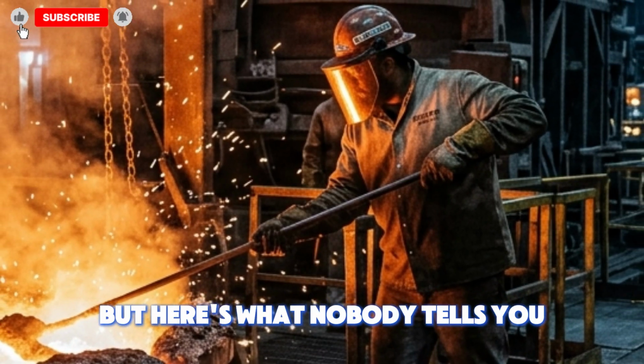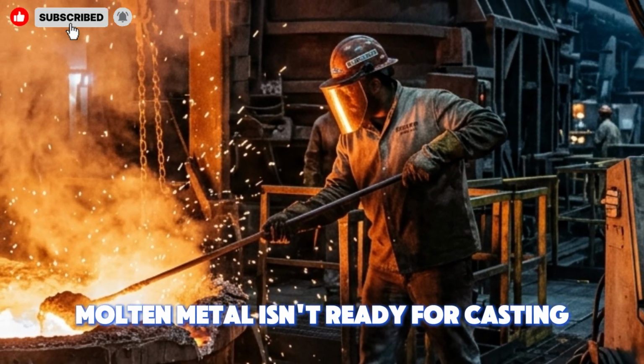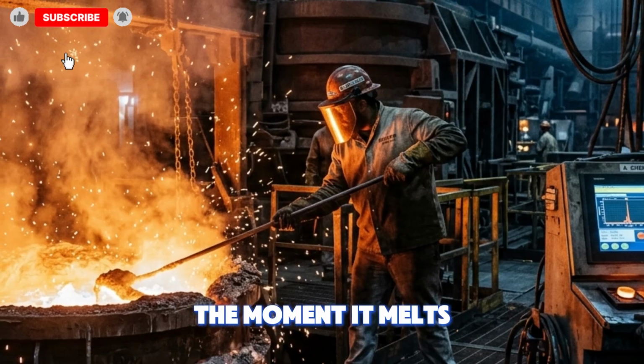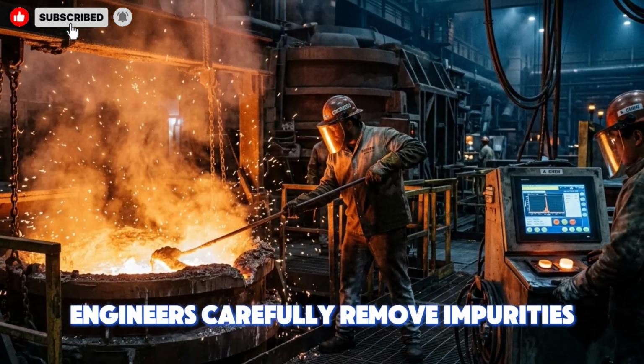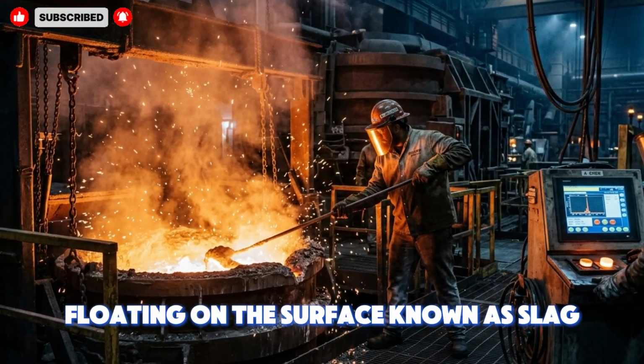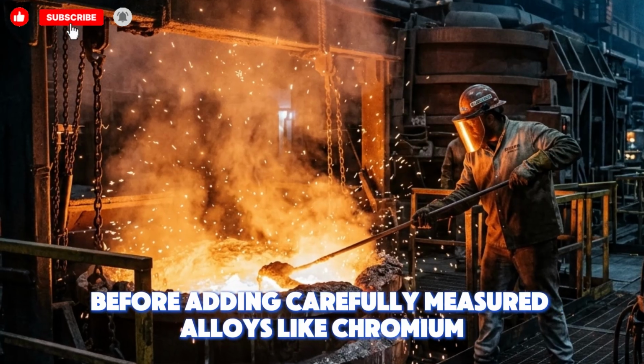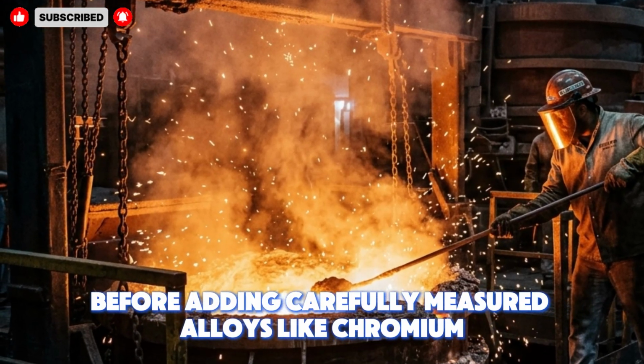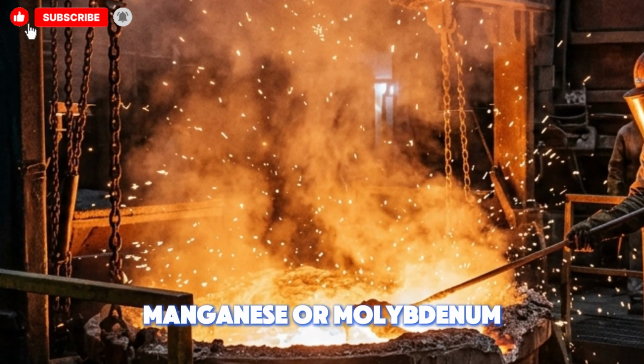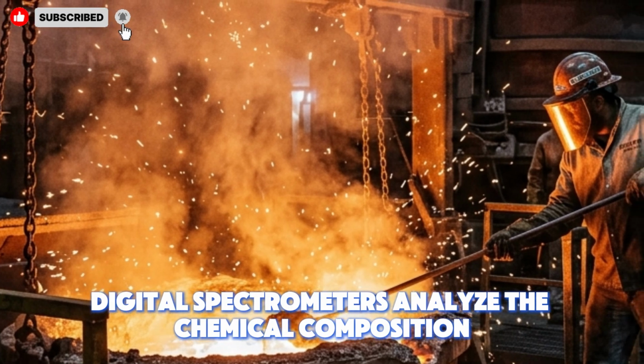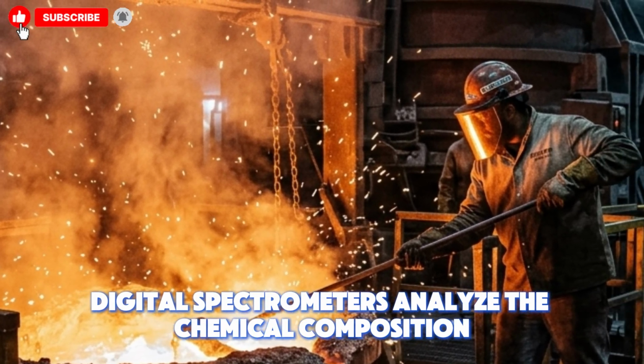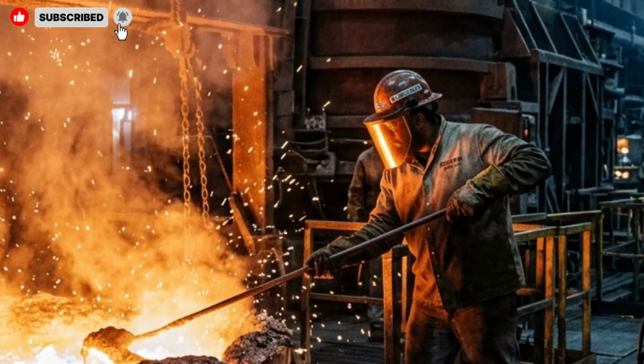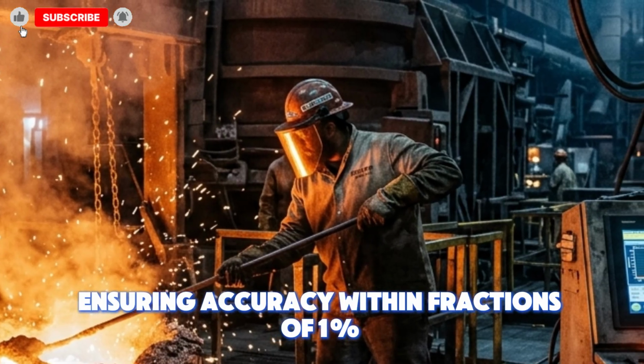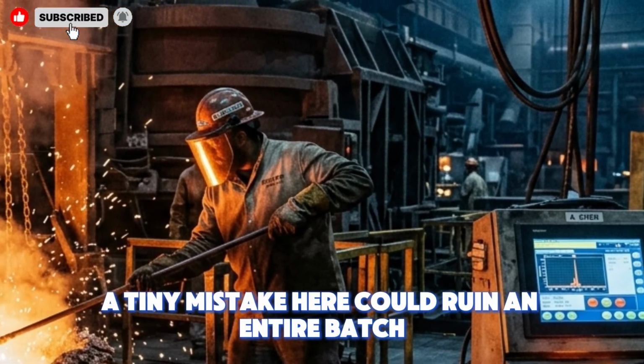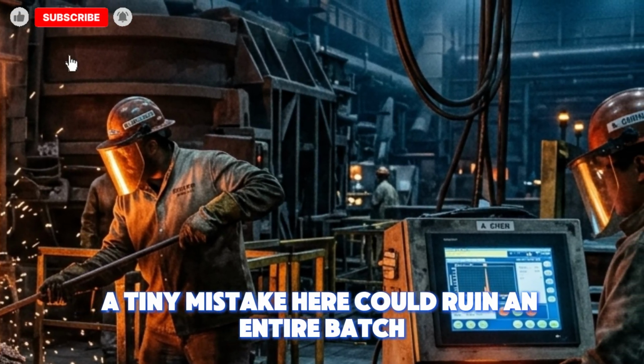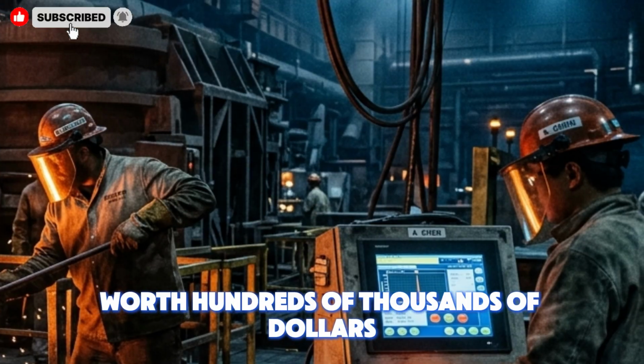But here's what nobody tells you. Molten metal isn't ready for casting the moment it melts. Engineers carefully remove impurities floating on the surface, known as slag, before adding carefully measured alloys like chromium, nickel, silicon, manganese, or molybdenum. Digital spectrometers analyze the chemical composition in less than 60 seconds, ensuring accuracy within fractions of 1%. A tiny mistake here could ruin an entire batch worth hundreds of thousands of dollars.